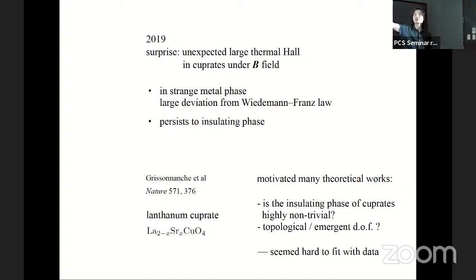And in the strange metal phase, they found that the thermal Hall coefficient has a very large deviation from what you would expect from the Wiedemann-Franz law for the electrical degrees of freedom in the strange metal. Deviation from Wiedemann-Franz law is quite common, right? Right. So at the beginning, they thought the deviation is due to its being a strange metal, so that the charge is not a Fermi liquid, but something very exotic. But then they did more experiments, and they found it even in the insulating phase.